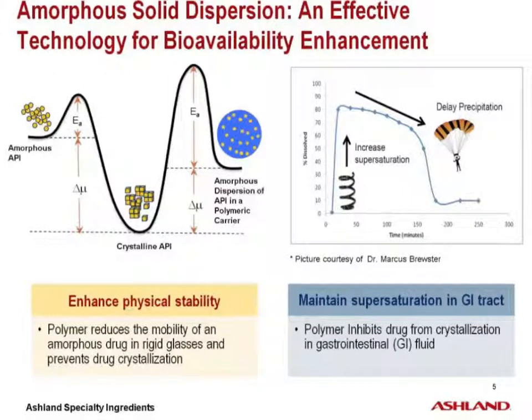Amorphous form is a thermodynamically unstable configuration of the molecules. Therefore, it has higher apparent solubility and dissolution rate compared to its crystalline form. Meanwhile, the thermodynamic instability also brings about a stability issue, and crystallization tends to happen very readily and rapidly. Therefore, in most cases, the addition of a polymeric carrier is necessary to stabilize the amorphous material by reducing its mobility.